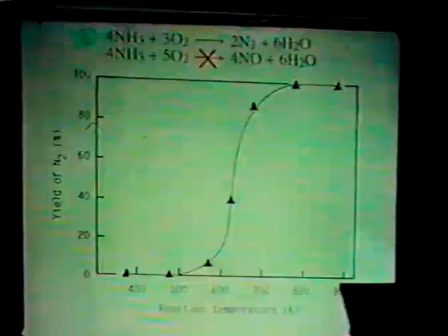This difference could be explained by side reaction between ammonia and oxygen as shown here. These side reactions lead to difference in the conversion and yield, that is the high ammonia conversion and the low NO conversion compared with the nitrogen conversion. In order to confirm the contribution of these reactions,